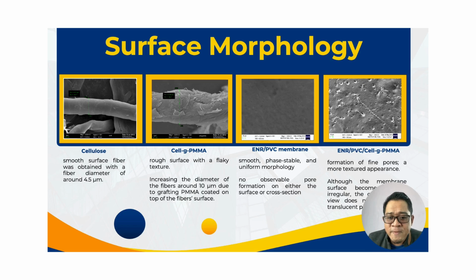And then the ENR PVC membrane shows a smooth, phase-stable, and uniform morphology. No observable pore formation either on the surface or cross section. And lastly, for ENR PVC cellulose grafted PMMA, there is the formation of fine pores with a more textured appearance. Although the membrane surface becomes irregular, the view does not show translucent pores in the sample.